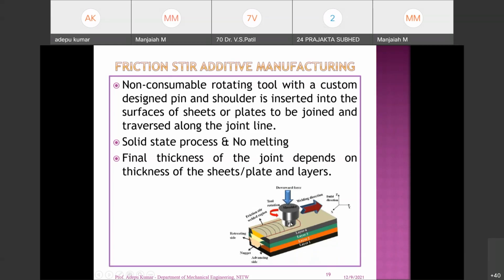So once the pin has completely gone down, the other portion you have is the shoulder. The shoulder contacts the top surface of layer 4. It is still rotating, because this part is stationary and this one is rotating. Due to that, a lot of friction is developed. That friction increases the temperature at the bottom of the shoulder portion of layer 4. Again, that portion reaches its recrystallization temperature, and then you can move the tool in this direction. So you rotate anti-clockwise and move in this direction after reaching the recrystallization temperature of the material.